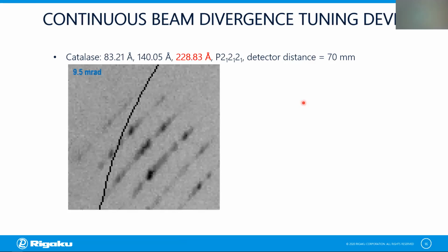Here is an example again of a protein crystal. This time, this is a crystal of catalase, which has an even longer unit cell edge of almost 230 angstroms. This time, I brought the detector to 70 millimeters, which is really short again, according to that unit cell edge. And then, of course, with the full beam, I couldn't see reflections. All I had is streaks of diffraction.